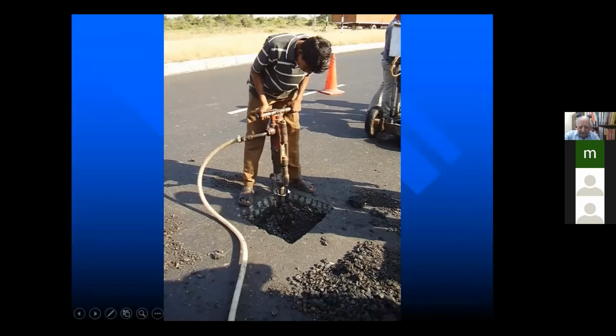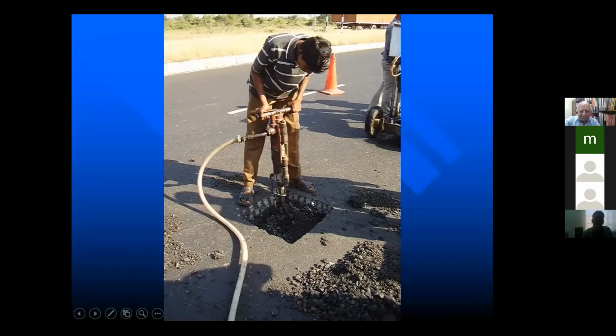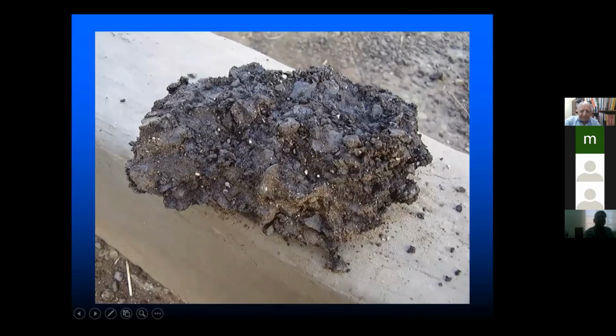So what we did was that we found out that the BC, which was recycled, 50 millimeter, 52 millimeter, was very good, intact, no problem. But below that, the DBM layer, which was already existing layer, was just crumbling. A lot of stripping has taken place. It was crumbling. So here is the picture. In the DBM, a lot of stripping. You can see again particles are mixed. There is no bitumen film here. 50%. I mean, you can break this with your hand.